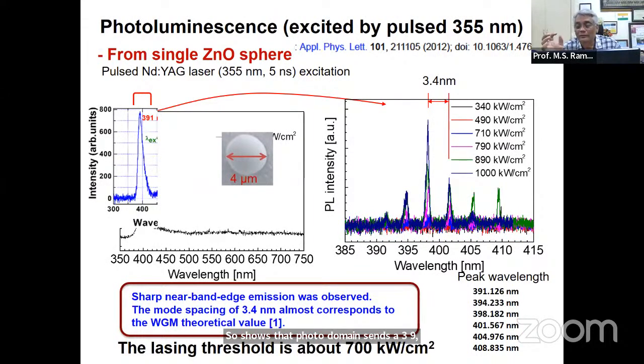But the moment you look at the PL emission from zinc oxide microspheres, that same sharp 391 peak splits up into smaller peaks. And as you increase the laser power, at a certain power density, you start seeing lasing action.